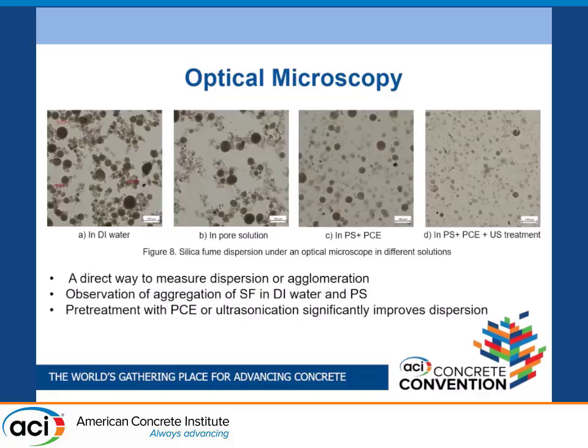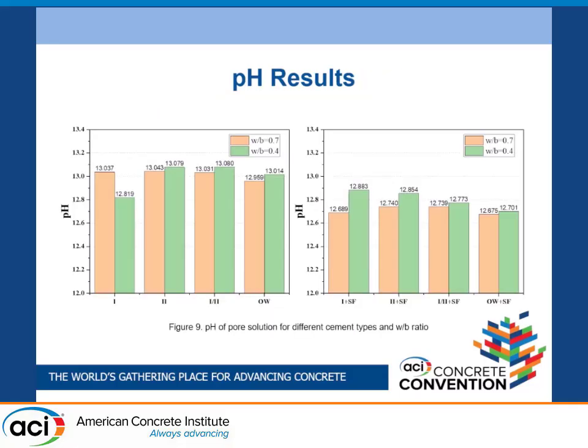That's the reason whenever we mix UHPC, we always pre-treat the silica fume with some aggregates or some method so that they are dispersed better. And the next thing I want to point out is the pH results.